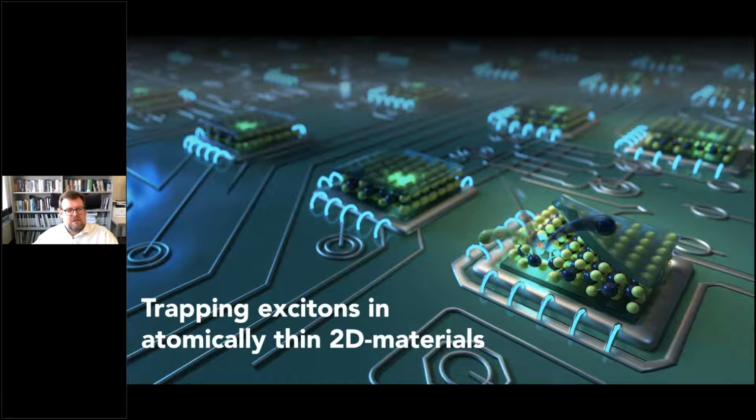Of course, this is a very futuristic picture, but we'd like to come very locally with a helium ion, focus it to a couple of nanometers in size, and try to create monotypical point defects which are optically active. And it turns out this produces a trapping potential for electron hole pairs. It produces single quantum emitters site selectively inside this material. So I'll show you that we can use these things to generate site selectively bright and very sharp quantum emitters where you pre-program the positions.